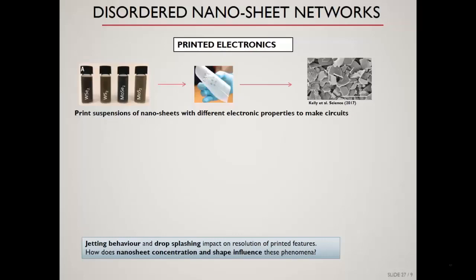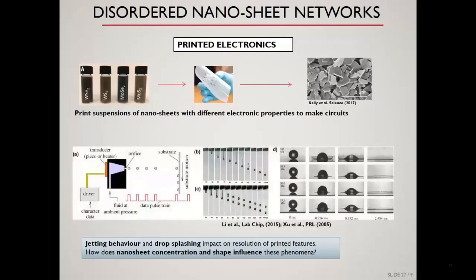Now the problem is, in order to do this, you need to understand the fluid dynamics. For example, typically in inkjet printing, you force it through some 20, 30 micron nozzle, and you get the so-called jetting, and then it splashes on the substrate. In this case, you can see you get this corona, and little droplets are emerging, and that of course affects the resolution of your printed features. This doesn't typically happen on paper, because it's porous and it sucks up the liquid, but on hard substrates that are used for this type of application, you can get that. And that depends on all sorts of things like surface tension and viscosity.